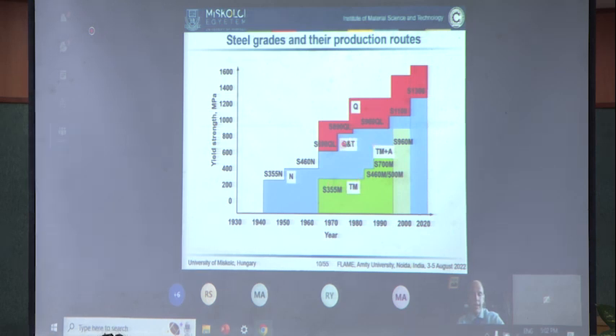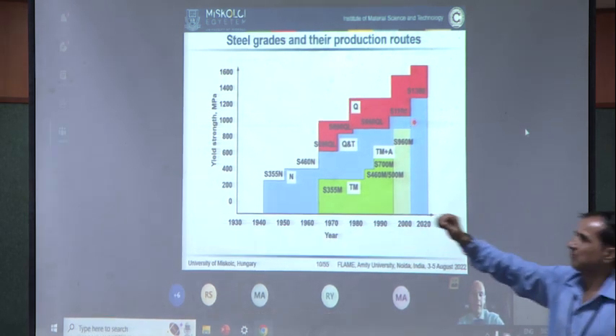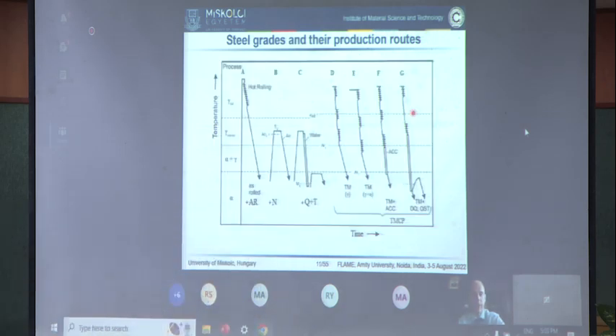As you can see, with this technology, we can reach nowadays even 960 megapascal. So there is approximately a 15-20 year difference between achieving the same strength grade by the different kinds of technology, but the TMCP process can be considered quite competitive compared to quenching and tempering.